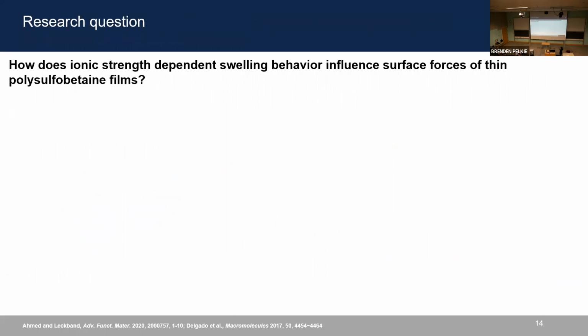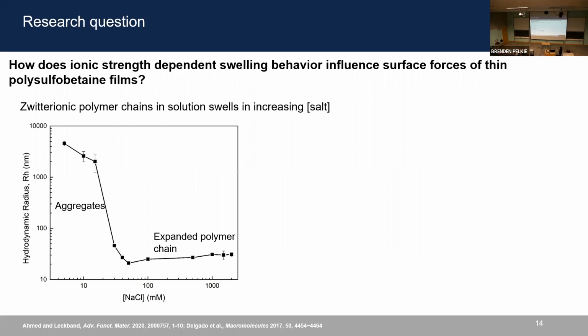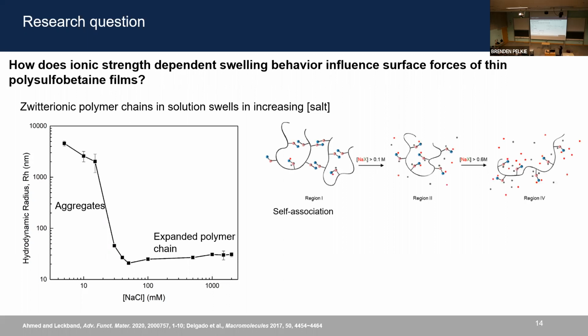So the research question that we addressed is, how does ionic strength-dependent swelling behavior influence the surface forces of thin polysulfobetaine films? In solution, it is known that zwitterionic polymers swell or increase in size with increasing salt. So if you measure the hydrodynamic radius with dynamic light scattering and plot it with increasing salt concentration, then we see that at lower salt concentration, there are huge aggregates that are formed because of excessive self-association, or the interactions between the side chains from the same polymer coil or with neighboring polymer coils.